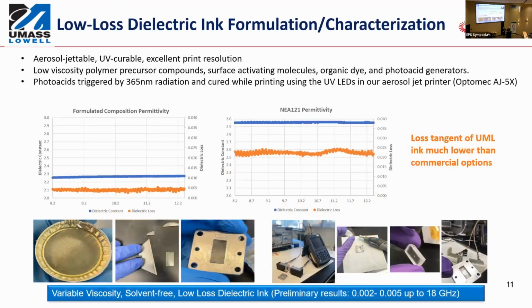All right, another key area for anyone in additive is developing low loss dielectric inks that we can actually print. So we have been working very recently on a variable viscosity, solvent-free, low loss dielectric that can be printed using the aerosol jet, so you can get very thin lines, and also using other printers like microdispensing, Nordson and things like that. It is UV curable, but can also be thermally cured. So far, we've made measurements up to 18 gigahertz, and we're within the 10 to the -3, which is an order of magnitude better than the commercial inks out there.